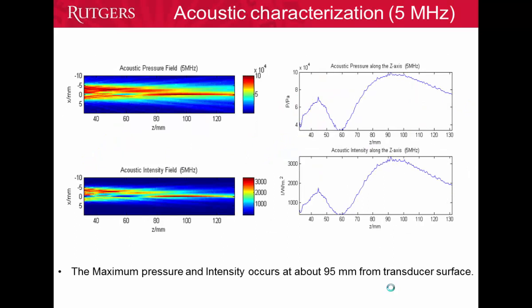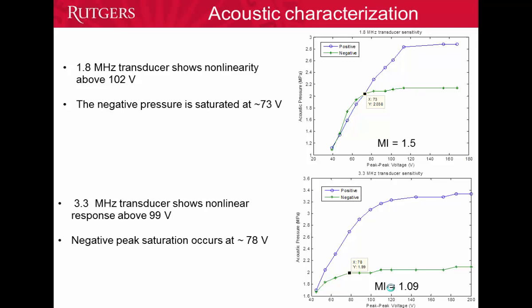Here you can see the two-dimensional distribution of acoustic pressure field and acoustic intensity aligned along the z-axis for the 5 megahertz transducer. The acoustic pressure and the intensity for this transducer reach the maximum at 95, which is the natural focal point because we didn't use any lenses. For the 1.8 megahertz transducer, you can see that the negative pressure is saturated at 73 volts, and the nonlinearity happened after 102 volts, and the mechanical index is 1.5. The 3.3 megahertz transducer has nonlinearity after 99 volts, and the negative peak saturation occurs at 78 volts with a mechanical index of 1.09.